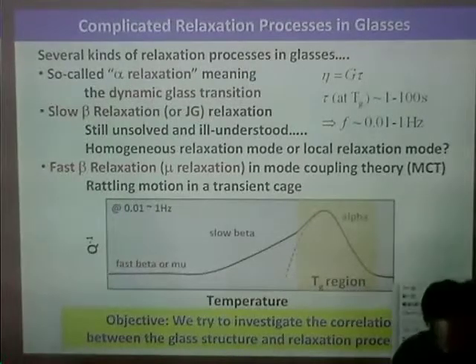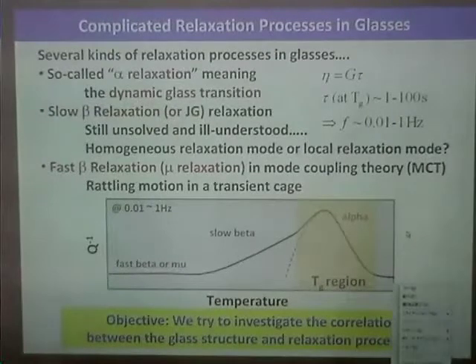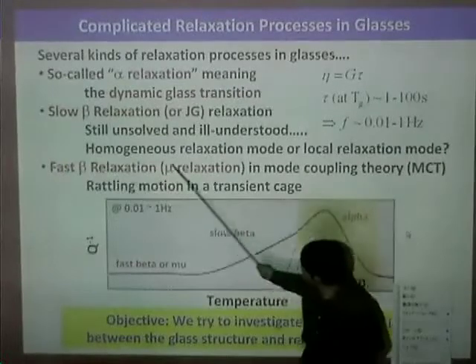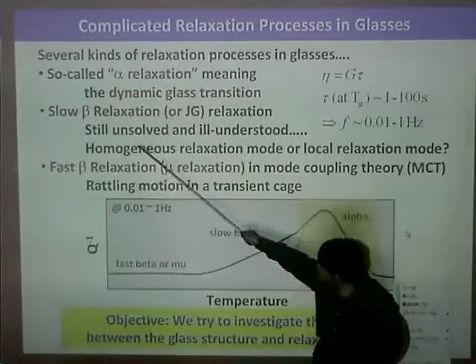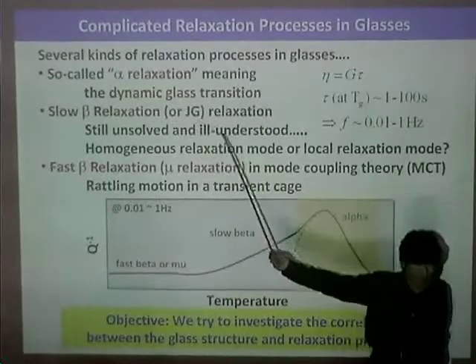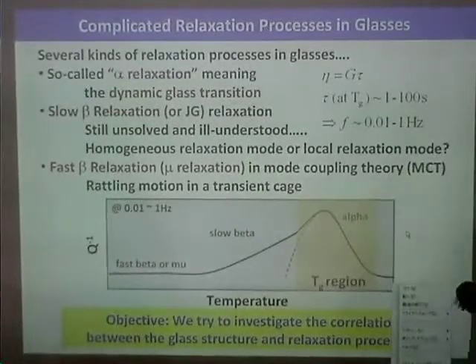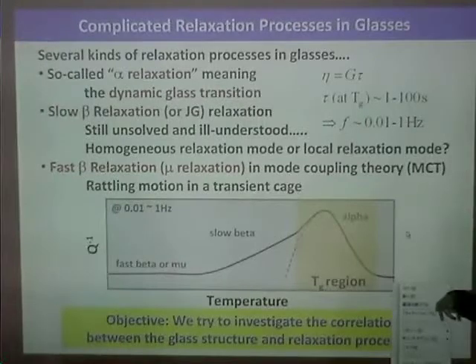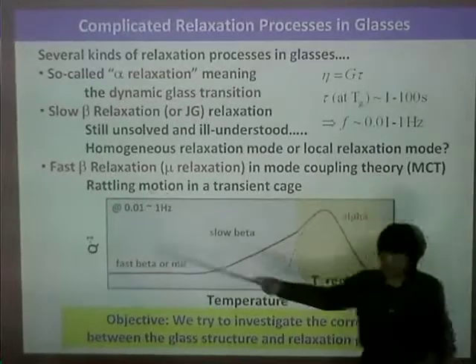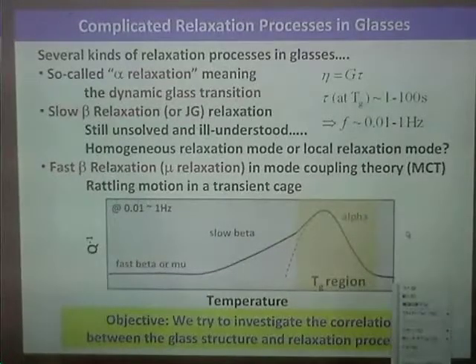Can you say a bit more about the distinction between the slow and the fast beta relaxation? Yes. The slow one is the so-called Johari-Goldstein beta relaxation, which occurs due to atomic jumps, with an activation energy. But the fast beta relaxation is considered to be a rattling motion of atoms in the cage in the glass.